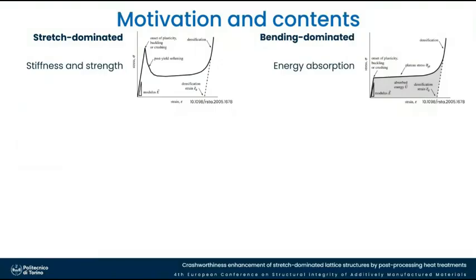So from a mechanical point of view, usually lattice structures are divided into those called stretch-dominated, characterized by high stiffness and high strength, and so they find application where stiffness and strength are required, and those called bending-dominated, which are instead characterized by a huge plateau of the stress, a huge amount of strain that can be accumulated, and that usually find application where energy absorption is instead required.